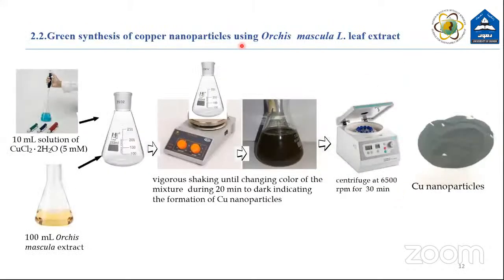Green synthesis of copper nanoparticles using Orchis. 10 milliliters of copper salt solution is mixed with some milliliters of plant extract, then shaken for 20 minutes until the color changes, which indicates the formation of nanoparticles, and then by centrifuge we can separate the nanoparticles.